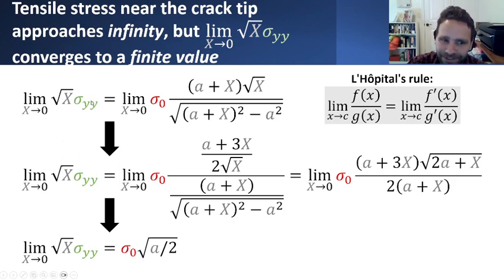Sigma yy goes to infinity, but if you multiply it by the square root of x, you actually get a finite value, and it looks kind of like this. It converges to sigma naught, the far field stress value, times the square root of a divided by 2. So while it doesn't really make sense to look at stresses in the vicinity of the crack tip, we can still look at other things.